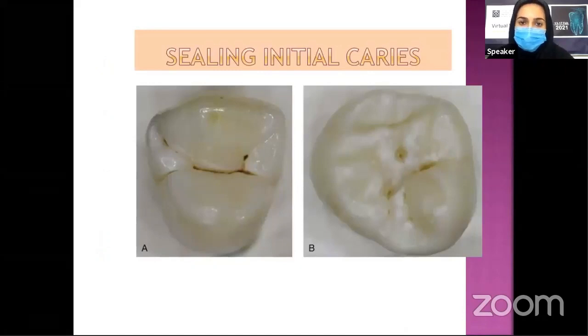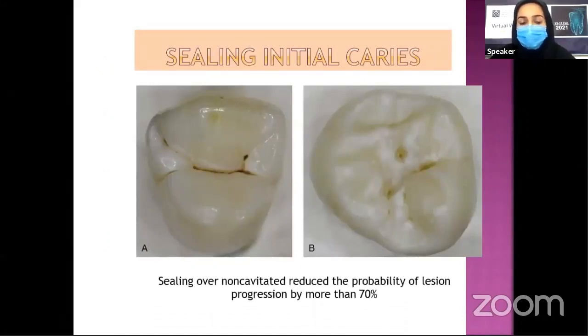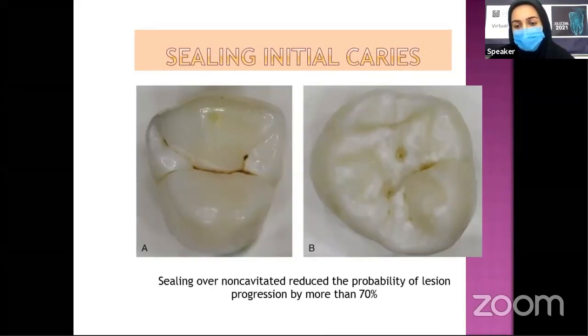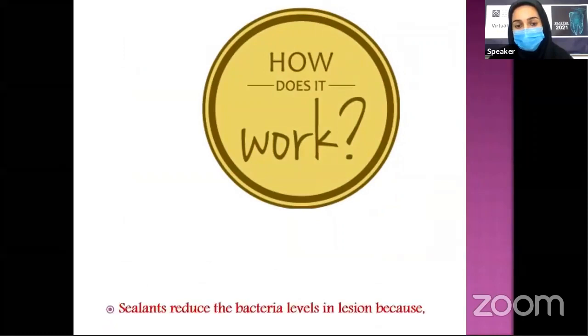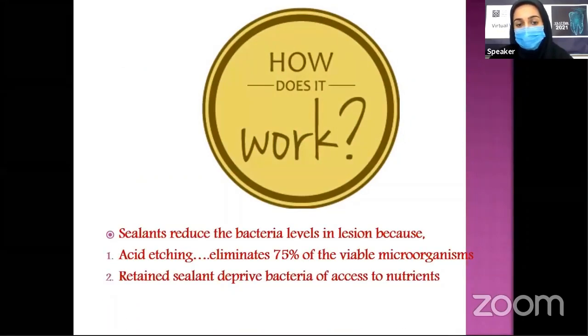And what about sealing initial caries? Today, it has been shown that sealing over non-cavitated lesions reduced the probability of lesion progression by more than 70%. And how does it work? The sealant reduces the bacterial levels in the lesion because acid etching eliminates about 75% of the viable microorganisms, and the sealant also deprives bacteria of access to nutrients, and so they will die.